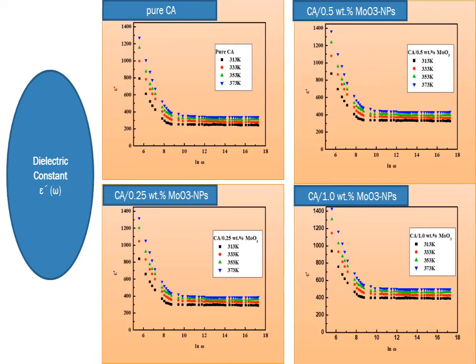According to frequency, we observed that the dielectric constant has a high value at low frequency and decreases with increasing frequency. We can say this is due to the dipole having sufficient time to orient with the electric field at low frequency, but at high frequency of the electric field, the dipole can't follow the electric field, and then the dielectric constant decreases and reaches saturation.